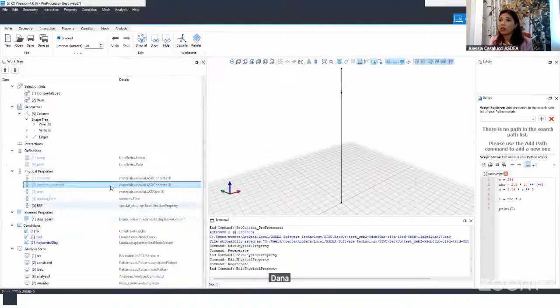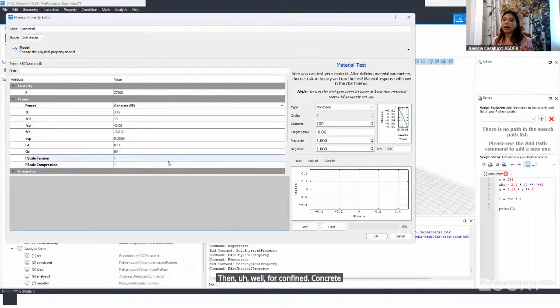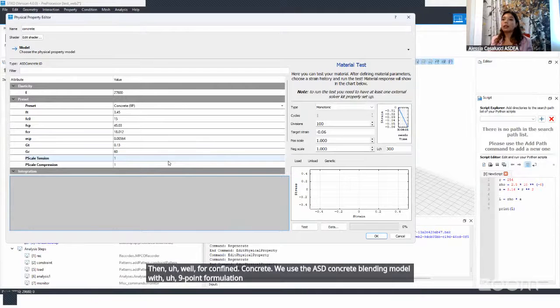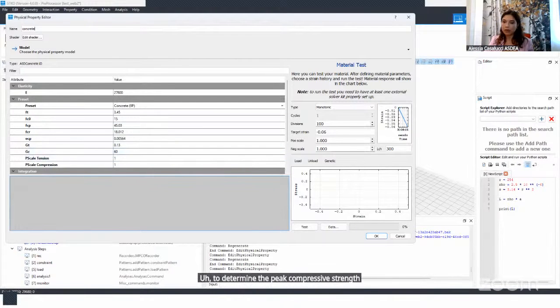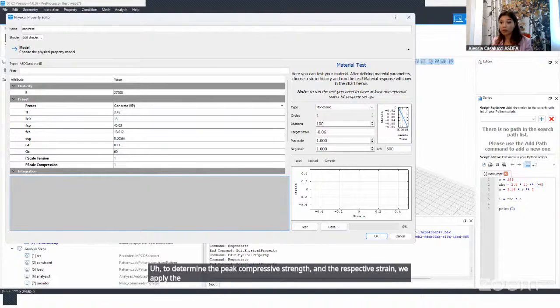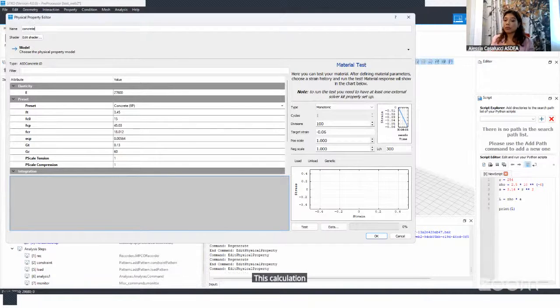Then, for the confined concrete, we use the ASDConcrete1D model with the 9-point formulation. This model allows us to represent nonlinear behavior under both compression and tension, including softening and fracture, to determine the peak compressive strength and the respective strain. We apply the Mander formula, which relates the confined and the unconfined compressive strength through the lateral confining pressure generated by the spiral stirrups. This calculation helps to ensure that the behavior of the inner core is realistically represented.